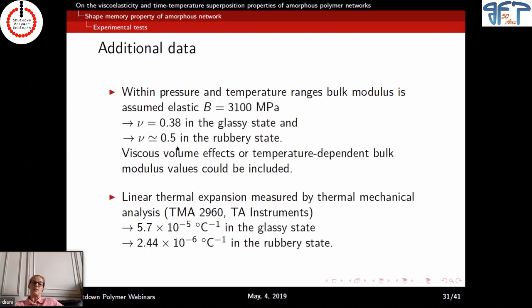And you can see that it's very close to 0. So the Poisson ratio is very close to 0.5. Okay, so the rubbers are incompressible, is it? They're quite incompressible. They're never fully incompressible, because the bulk modulus is closer to 3,000, which is not gigantic, right? But if you look at the change of volume when you do a uniaxial tension, it's close to 0. So that's why we say it's incompressible. But from a mechanical point of view, a bulk modulus of 3,000 is far from being incompressible, right?